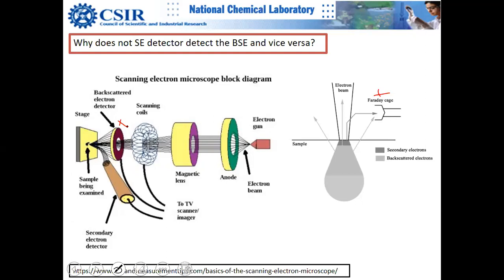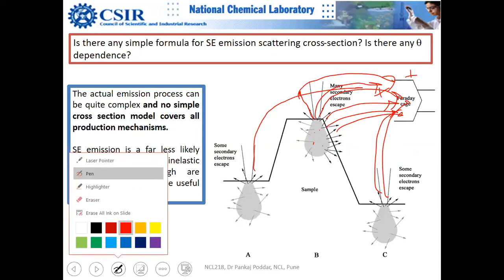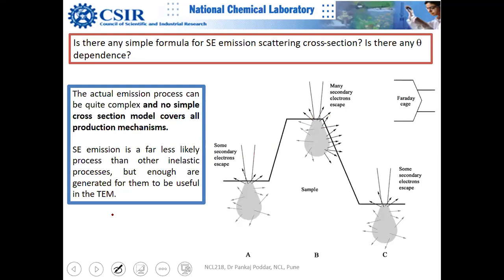There will be more scattering from gold atoms than from copper or nickel. Without any attracting force, backscattered electrons travel more directly. If no positive voltage were applied to the secondary electron detector, only those electrons scattered directly toward the detector would be detected, and the signal would be very weak — electrons going in other directions would be lost.